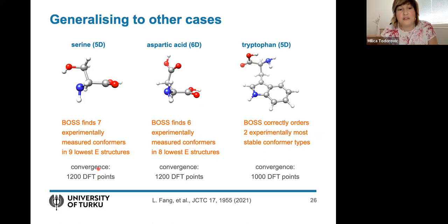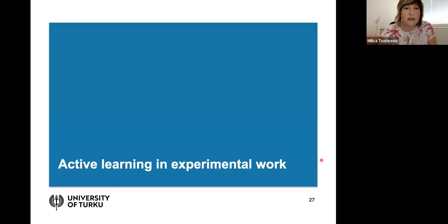And I want to stress that to converge these energy landscapes in 5 and 6D and to extract all the minima, it took only about 1,000 DFT calculations. So this is relatively fast for sampling, because typically these conformer search problems are cracked with genetic algorithms or minima hopping. And the typical amount of structures you need to compute there is about 10,000. So we were able to reduce this by approximately an order of magnitude, and this is due to this smart sampling that creates maximally informative data sets.